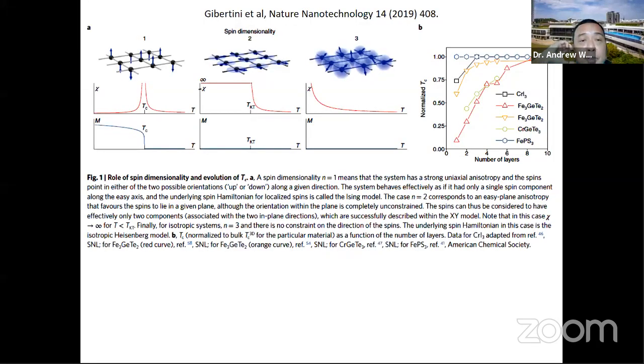So this diagram from the review shows that at the top left, you have a spin dimension 1, you have an Ising spin system. So it's a 2D system where spins are up or down. As you can see, you have a finite Curie temperature and you can get this phase transition, and it's magnetic at low temperatures below the Curie temperature. And then you have this system where you have spins that can be in the plane. It's explained by the XY model, and the isotropic system where the spins can be anywhere.